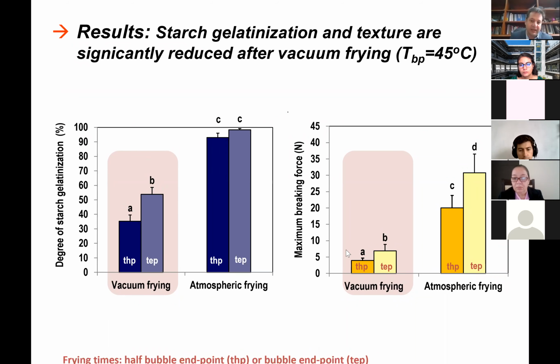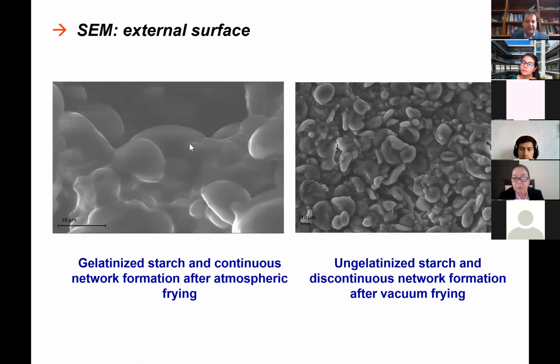This was reflected as well in the texture. Here we have the maximum breaking force, and we can really see that vacuum frying samples are much more brittle compared to atmospheric ones, especially when preparing a dough, like the one I just referred to previously. So it's very important, as I referred before, that we are going to be able to reduce starch gelatinization, but at the same time, we will have a much more fragile structure. And this can be observed using environmental scanning electron microscopy, where we can really see what happened to the gelatinized starch within the structure as compared to the ungelatinized starch that forms really a discontinuous network in vacuum frying, which is very much related, or directly linked, I would say, to the texture that we were able to measure using texturometry, as I previously referred.